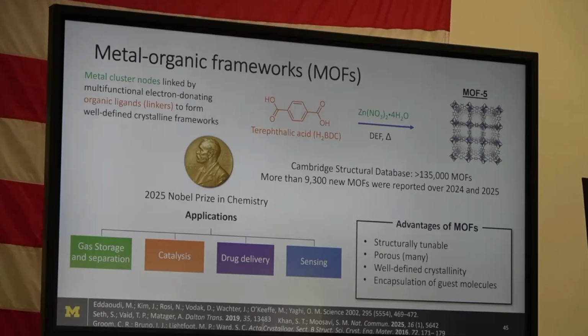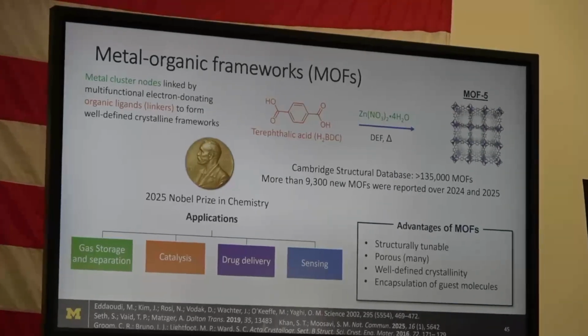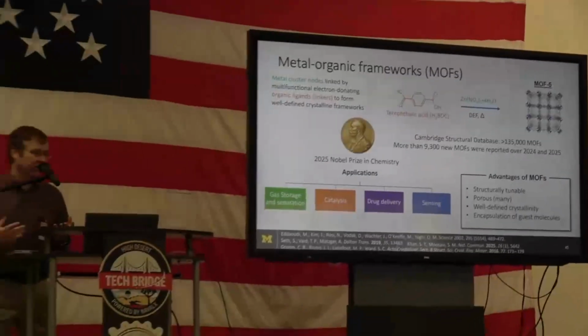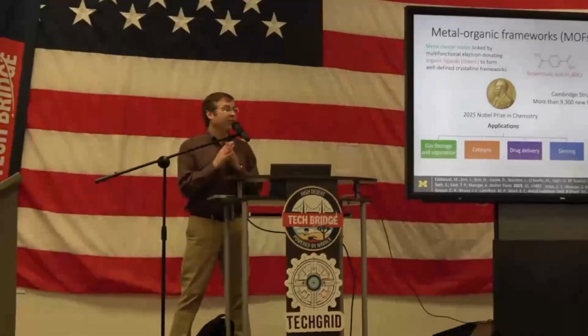So we thought if we used a porous MOF, what you can do is take that MOF and, through a process called activation, remove all the guests out of the pores. And then that MOF is very hungry for anything to go into those pores. So unlike co-crystallization, where it's happy to form pure A and pure B, there is a strong driving force for things to enter that MOF. And that's what we were going to do. And we're going to start with these kinds of porous MOFs.